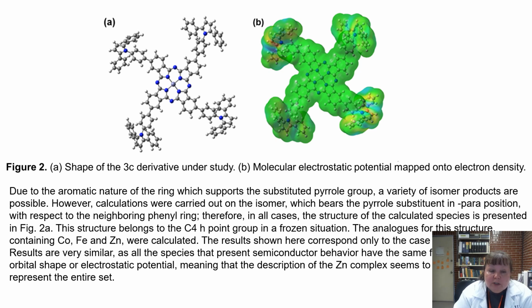Due to the aromatic nature of the ring, which supports the substituted pyrrole group, a variety of isomer products are possible. However, calculations were carried out on the isomer which bears the pyrrole substituent in para position with respect to the neighboring phenyl ring. Therefore, in all cases, the structure of the calculated species is presented in figure 2a. This structure belongs to the C4h point group in a frozen situation. The analogues for the structure containing cobalt, iron, and zinc were calculated.